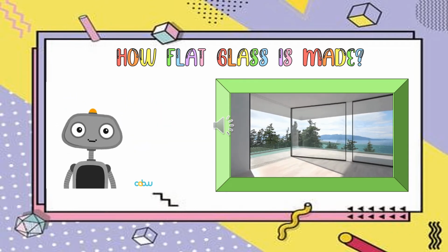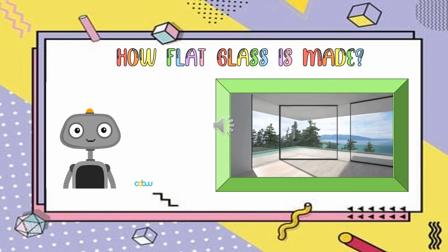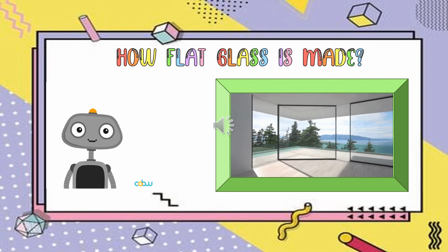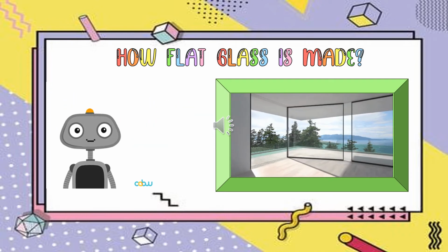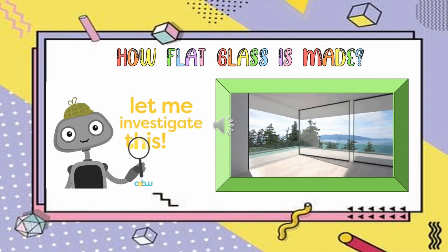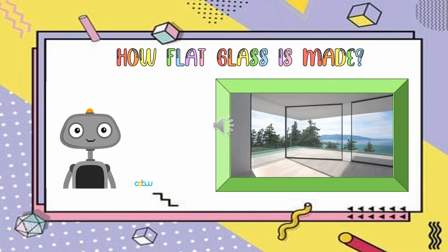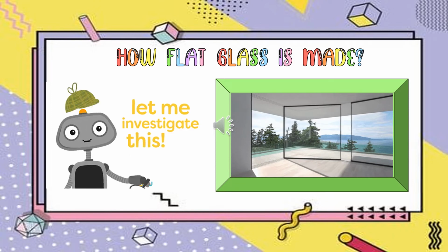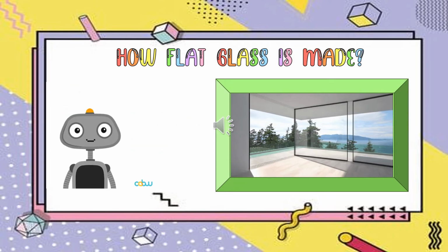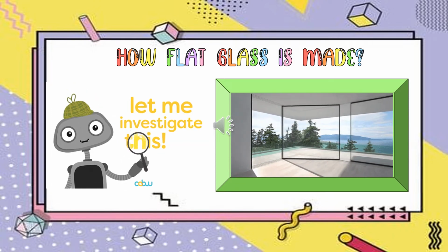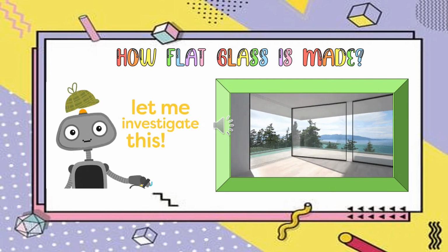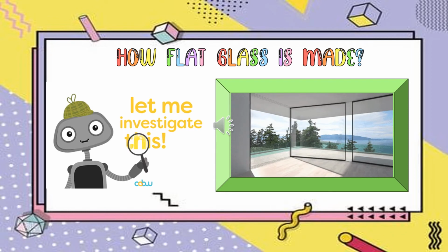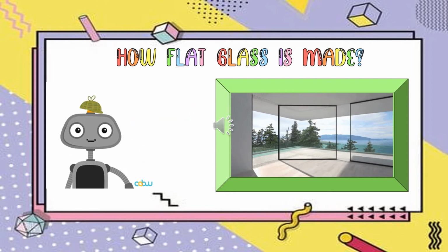To prevent the surface from oxidizing with the atmospheric oxygen, the vat is placed under a protective gas atmosphere. This atmosphere must be carefully controlled since its composition is instrumental for the property of the contact surface between the glass and the tin, which in turn influences the thickness of the glass sheet.